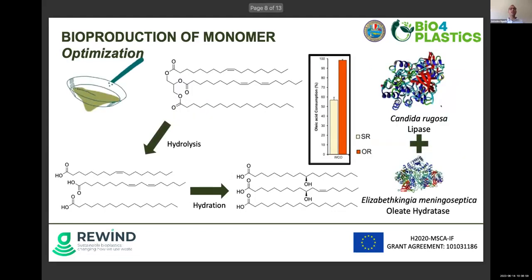But then what we could do is to optimize this part by using two different enzymes. One enzyme for the first hydrolysis, to produce free fatty acids, as you can see in the first step, and then the next step with hydration, as I showed before. The enzyme that we used for hydrolysis is, of course, a lipase. Lipases are able to hydrolyze ester bonds in triglycerides, and then the oleate hydratase can hydrate specifically these unsaturated fatty acids. And we carried out all this process in one pot. So together, lipases and oleate hydratases can work together for the production of the monomers.